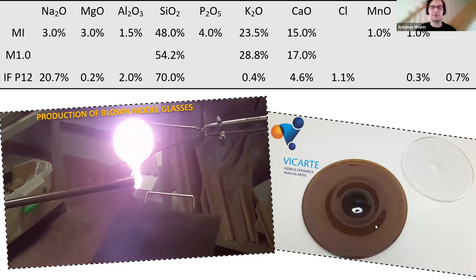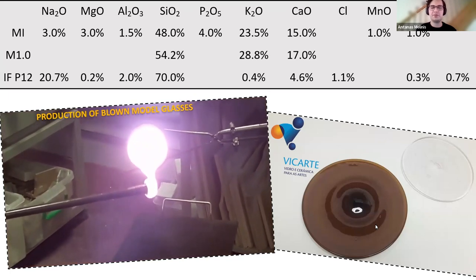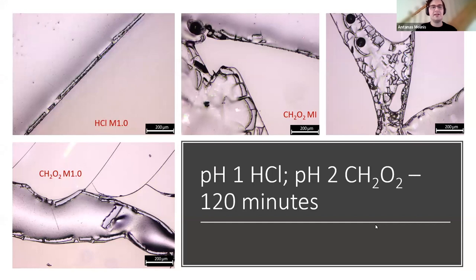They're made and blown into these rondelles that can be easily sliced up into squares for later testing. So one of the first goals was to create weathered layers in the model glass that would ideally be structurally and chemically similar to archaeological glass, and preferably not crizzled, so it could be induced later. I kickstarted with acid leaching, which is meant to be one of the fastest methods to accelerate corrosion. And indeed, it was very fast. Formic and hydrochloric acid solutions were sufficient to produce the layers in just 2 hours, and formic acid layers were generally thicker despite its higher pH.